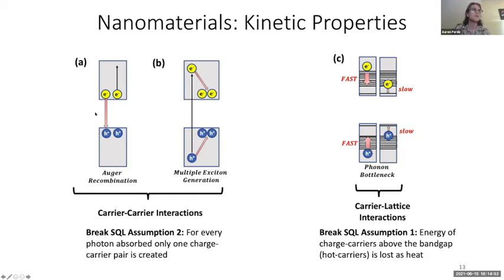And it's well known that one of the most prevalent recombinations is Auger recombination, where if you have multiple excitons in your material, instead of having two different recombinations of two excitons, one of the excitons will non-radiatively donate its energy to the other, which eventually turns into useless heat waste.